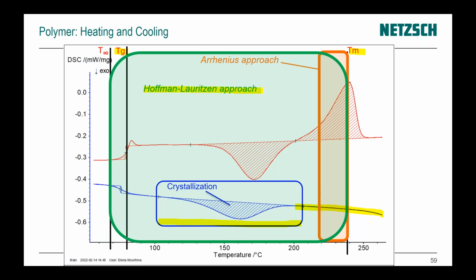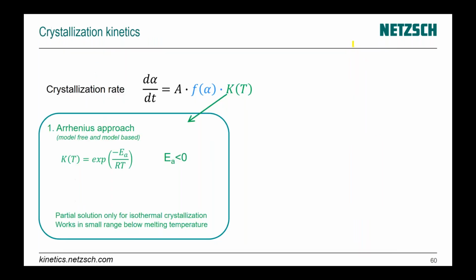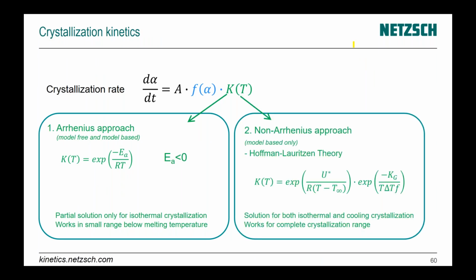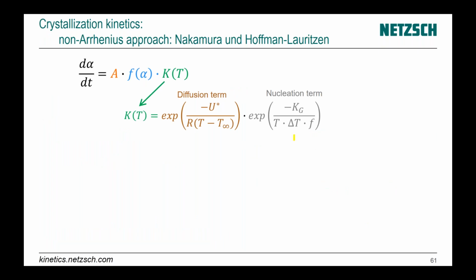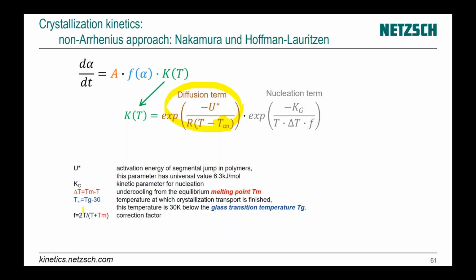It is the Hoffman-Lauritzen approach, which works from temperature T infinity, a little below glass transition, until the melting temperature. Again, for crystallization we have the Arrhenius approach and the non-Arrhenius approach with Hoffman-Lauritzen theory. This non-Arrhenius approach has 2 terms: the first is diffusion, which works near T infinity, near glass transition.